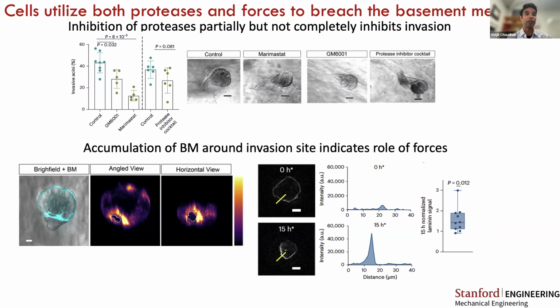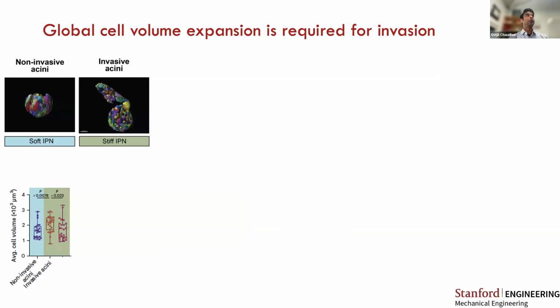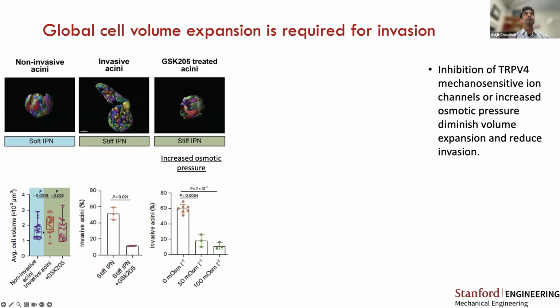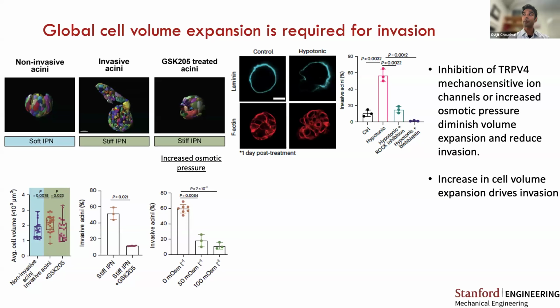Okay, so if forces are involved in basement membrane invasion, where could those forces be coming from? That was the next question we had. What we noticed is that the cells were a lot larger in these invasive structures relative to the non-invasive structures, about 2 times larger. And so we thought, could that be involved? So we inhibited cell volume expansion by inhibiting mechanosensitive ion channels, which are involved in cell volume regulation, such as TRPV4, or increasing osmotic pressure to prevent that volume expansion. And in both cases, when we prevented volume expansion, the structure became less invasive. Conversely, if we induced volume expansion in non-invasive conditions, that promoted invasion, as you see here. So using hypotonic media, invasion is enhanced.